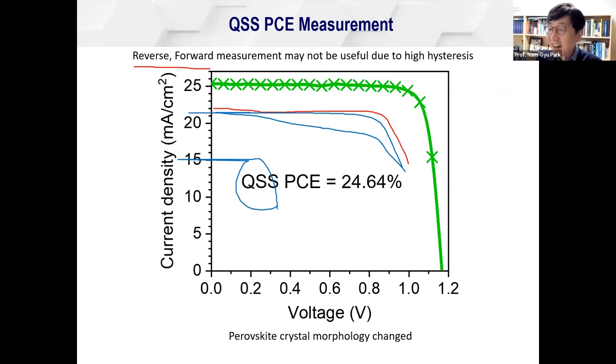Yeah, Monica, actually, high efficiency, high stability. I think everybody wants to know it, right? Yeah. If I knew the almighty additive, probably it would appear in Nature or Science. Anyway, we found in our group, and most groups, use MACl, methyl ammonium chloride, as an additive, and also cesium chloride in some cases. So methyl ammonium chloride and cesium chloride are so far the best, but for the future we cannot say those additives are still the best.